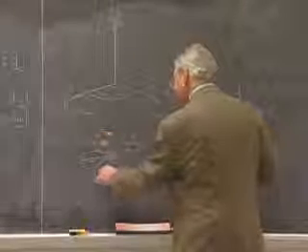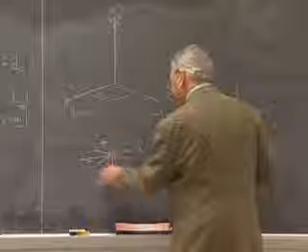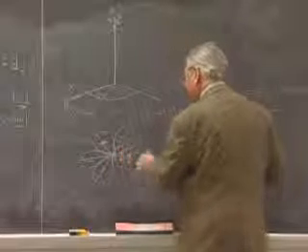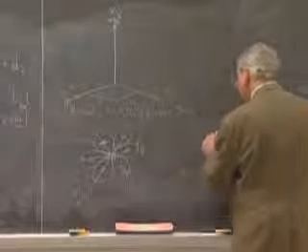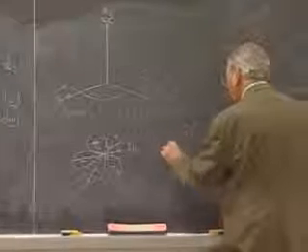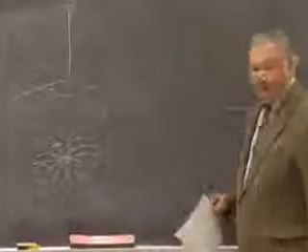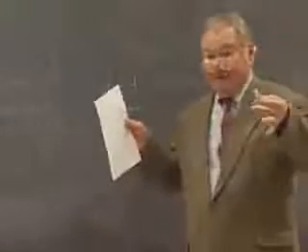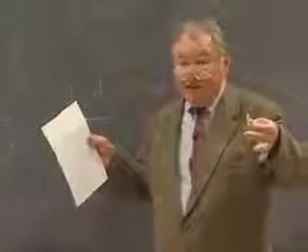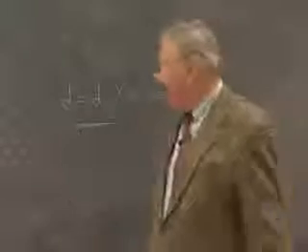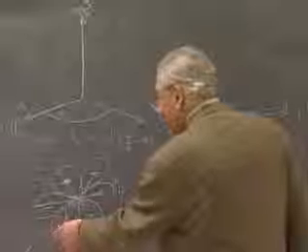So it's six-membered, 6 lobes. There is always a positive lobe opposite a negative lobe. Okay? And what this means is that the charge is of opposite sign on opposite ends of the twofold axes. So the response peaks up on twofold axes.